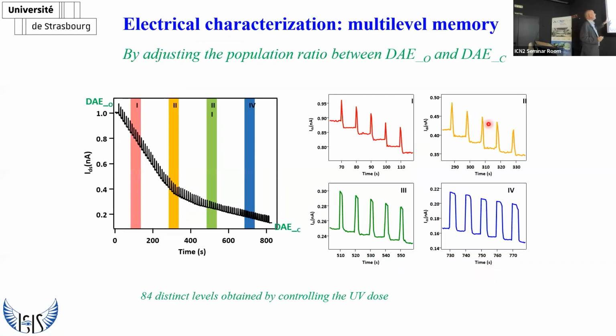Now you can actually use a fast laser, and with each pulse a finite number of diarylethene molecules pass from the open to the closed state, so you create more and more traps, and you decrease the current stepwise. This was done in my laboratory, and we are not equipped with a fast laser, so we can go only to 84 distinct levels. When this experiment was done, but using an organic semiconductor, in the lab in Nova Gorica by Guido Bratina, we could reach over 256 levels, so 8-bit memories essentially.